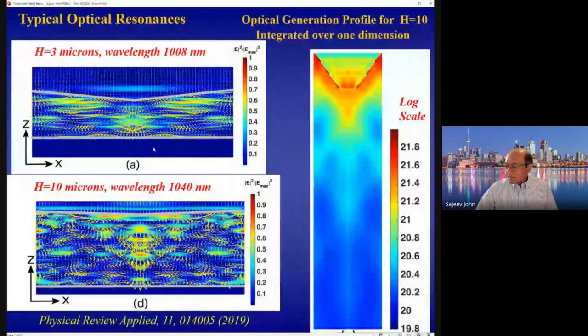So we can look in more detail at what is happening inside of each of these optical resonances. And this is a depiction of what happens at two particular resonances at 1008 nanometers and another one at 1040 nanometers. What is depicted here is the light intensity inside the structure. So this is the outline of the inverted pyramid here. This is the bottom rear reflector of the solar cell. This is for a 3 micron thick structure and below a 10 micron thick structure. You see high intensity spots where the light is being focused. That's the red regions. And the blue regions are where the light intensity is smaller.